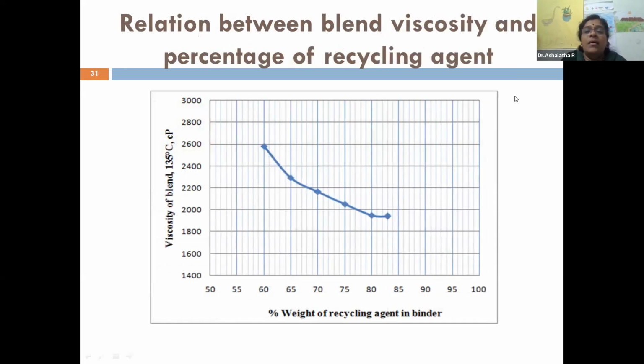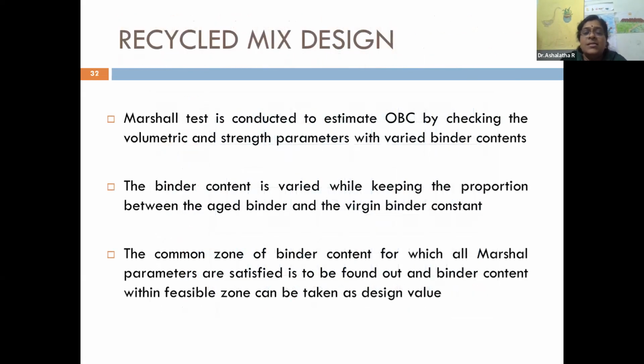This shows the plot of the percentage weight of the recycled binder against the viscosity of the binder at 135. The slide is not moving. Okay. The Marshall test is then conducted to estimate the optimum bitumen content by checking the various volumetric and strength parameters with varied binder content. The binder content is varied while this proportion between the aged binder and the virgin binder is kept constant. The common zone of binder content for which all Marshall parameters are satisfied is found out, and a binder content within the feasible zone is taken as the design value.